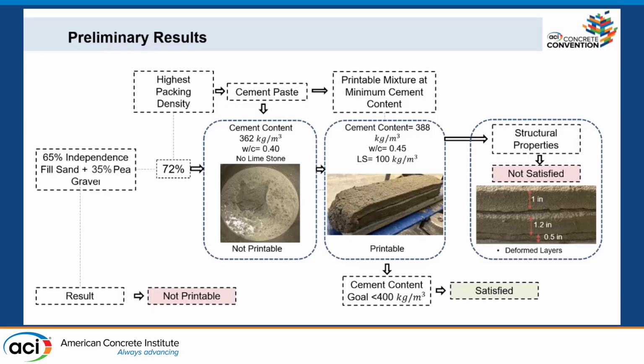For the next one, for the Independence fill sand and pea gravel, we have mixed around 65% and 35% of pea gravel, and the packing was 72% for the aggregates, and the 28% was the cement paste. For this one as well, with the cement content we got from the void content, it was not printable because the material was too stiff. Then we added some limestone. Also, we increased the water content ratio to make it a little bit printable, and it was successfully covering our cement content goal, which was below 400, and it was 388 kg per cubic meter. The problem was with the structural properties, and it didn't retain its shape because you can see the bottom layer was half an inch and the second layer was a little bit extra than our expected results. So this combination of mixture was also not printable for us.